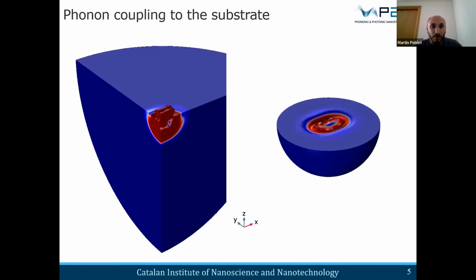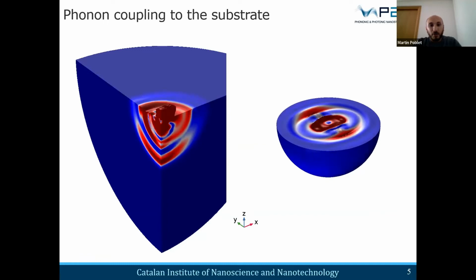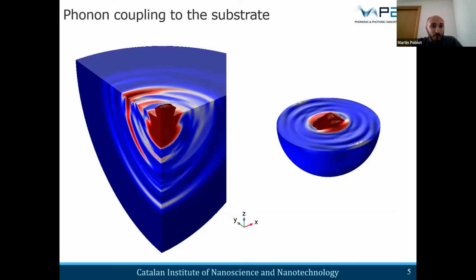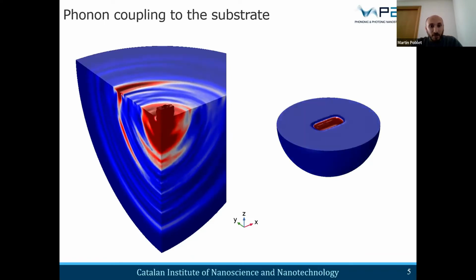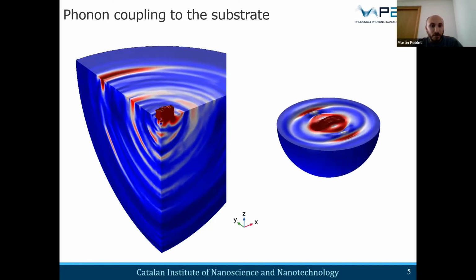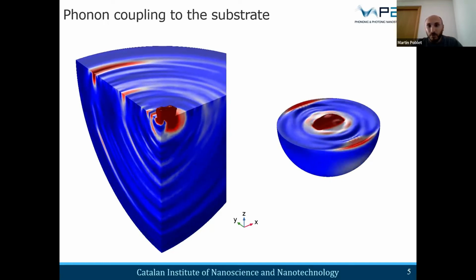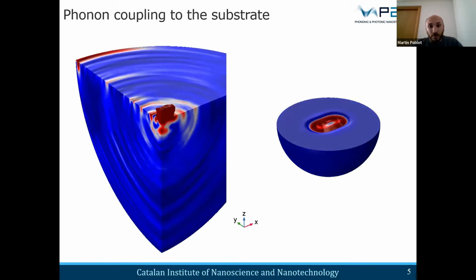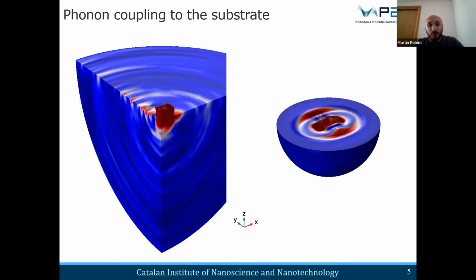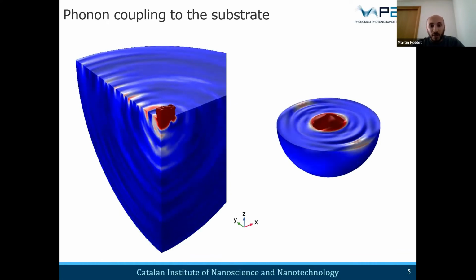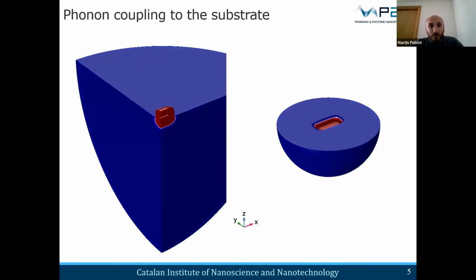In turn, due to the vibrations and the dynamic contact of the antennas with the substrate, mechanical energy will be transferred to the substrate, and thus the coupling of the nanoresonator with the substrate will result in the propagation of surface acoustic waves that will travel through the substrate, and which could be detected and characterized in the far field, in principle through the inverse phenomenon, that is the implementation of another plasmonic antenna as a receptor of these mechanical waves, which can be detected optically.